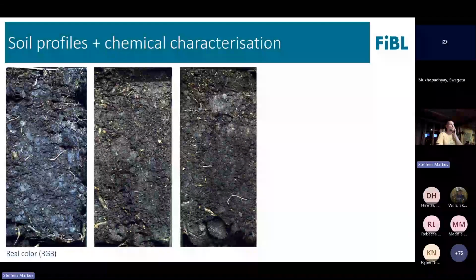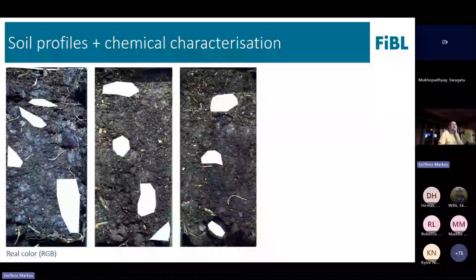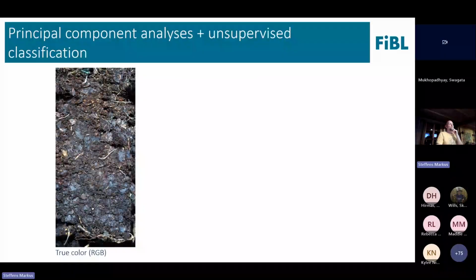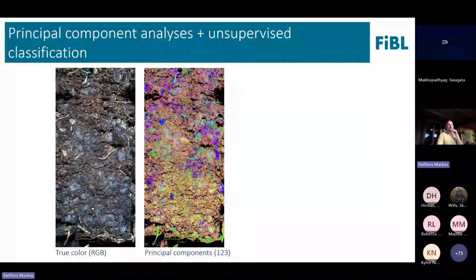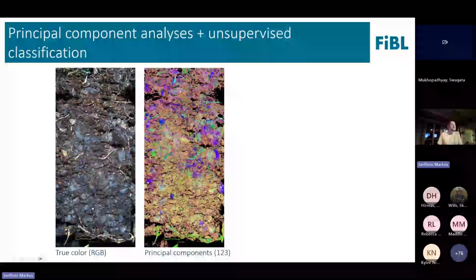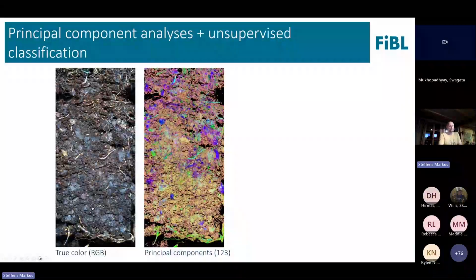And what we then did was the same again. So we took samples and analyzed them for carbon and nitrogen, and we used NMR to get information about the chemical composition of the organic matter. Here you see again the principal component analysis, and we see in this purely organic surface layer that there are different types of organic matter. And maybe you already recognize that there are some fresh roots, for example, and these roots show other colors, so other principal components, other spectral bands which are active when compared to these more thick materials, for example.